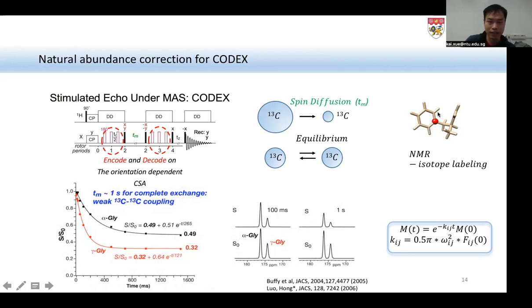So if I have two phenylalanine molecules here, and this labeled spin, they have different CSA, I mean their orientation is different. We have the spin exchange, polarization exchange, between these two spins, and then the curve will decay to half, and we know that yes, we have two spins close to each other. And if we have three spins, then the curve will decay to 1/3. How fast it decays is related to the dipolar coupling, and in other words, to the distance between these two spins.